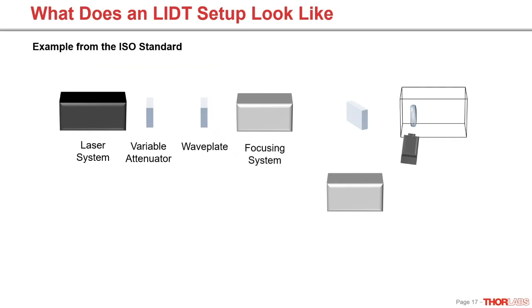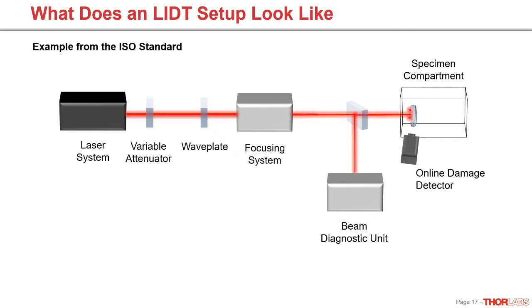You're going to need a focusing system because you're not typically testing with a raw beam. You have a beam diagnostic unit, the specimen compartment, because as I alluded to earlier, you probably don't want to be exposed to these parts as they're being damaged, and some sort of damage detector. So you can see a neat little animation of what's going on here. And this is obviously greatly simplified, but your typical test apparatus is going to follow this general format. Obviously, it's going to be a little more complicated.